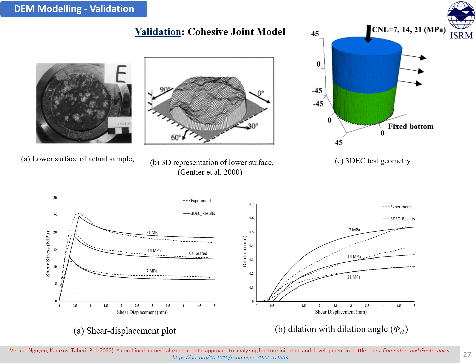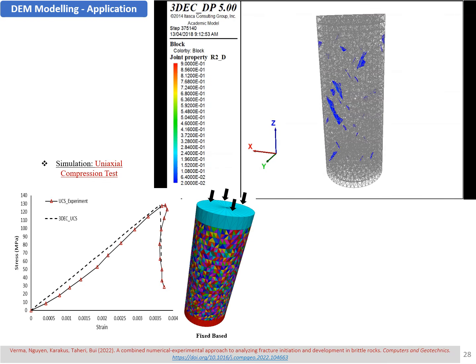Once implemented, the cohesive contact model was further validated using the experiments of mixed mode loading available in the literature. Once validated, this cohesive contact model, which was implemented in 3DEC, is now calibrated to the given rock type. In our case, that is bluestone. For this calibration process, we used two experiments. One is the uniaxial compression strength test, and the second one is the Brazilian disc test, that is the indirect tensile strength test.